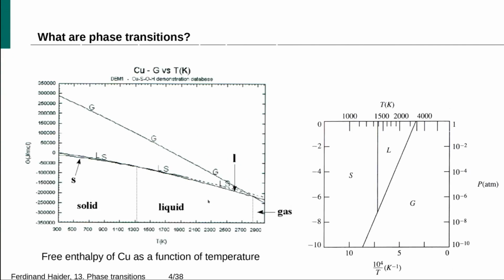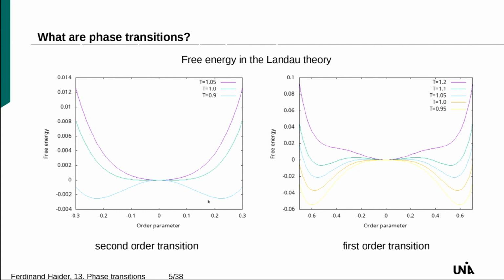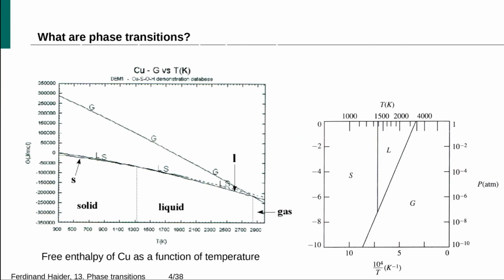Here I show a real sketch of these graphs for the case of copper, and you see that the difference in slope between the liquid and solid phase is pretty small, hardly visible. So here we have the solid phase, here the liquid phase, and they intersect here at the melting point - it's in Kelvin, around 1300 something.